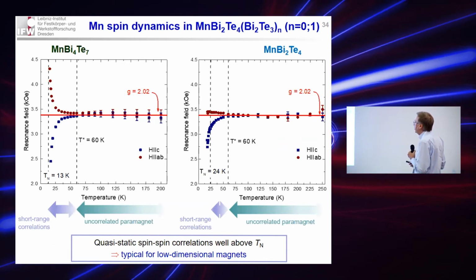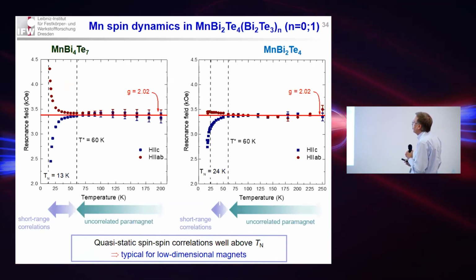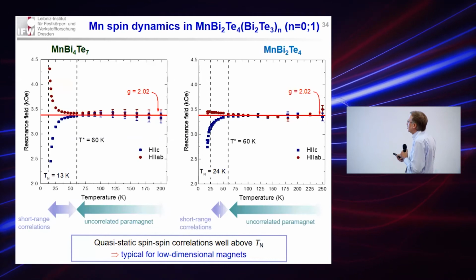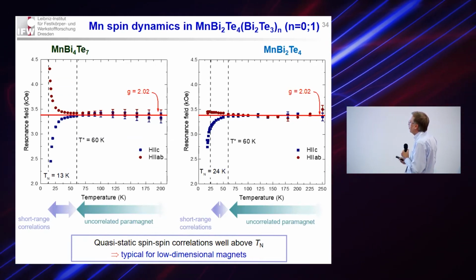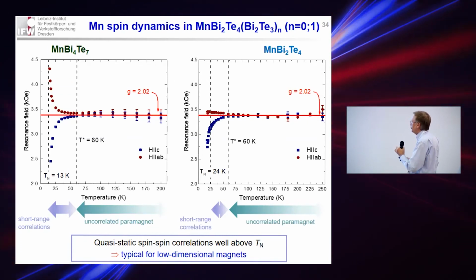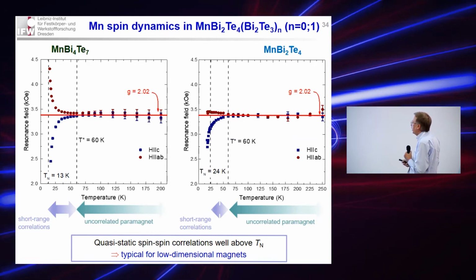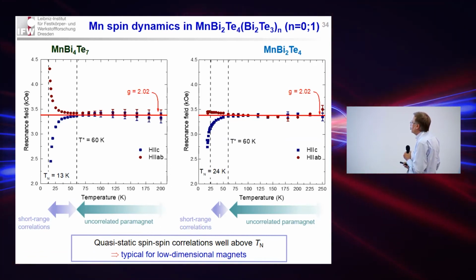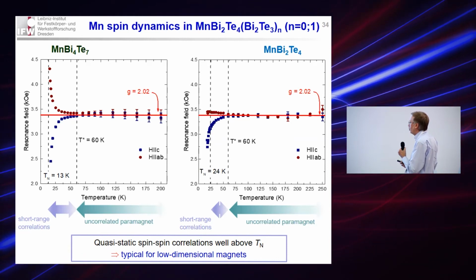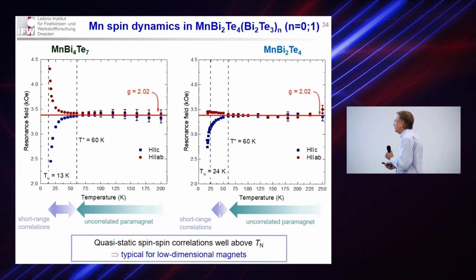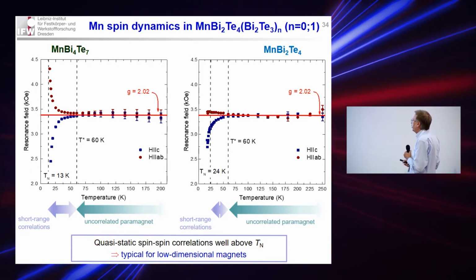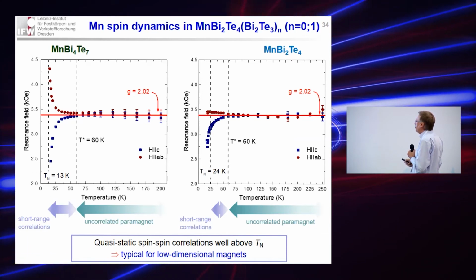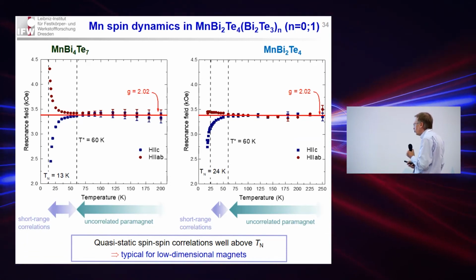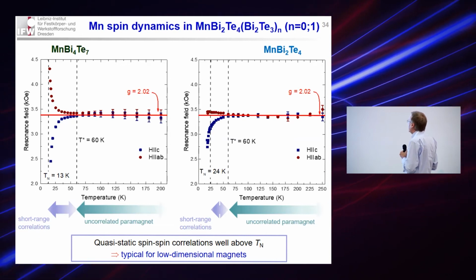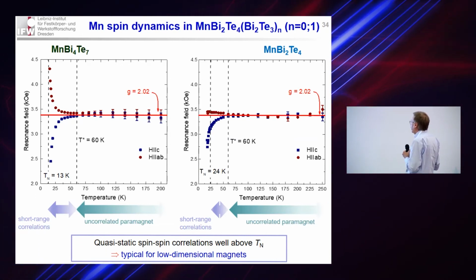As soon as we leave the magnetically ordered state, where there is a strong anisotropy of the resonant field regarding the orientation of the external magnetic field, we have some region where short-range correlations, very typical for low-dimensional magnets, a two-dimensional magnet, are present. But above a certain temperature the resonant field is truly paramagnetic, isotropic, and the same is true for both compounds.